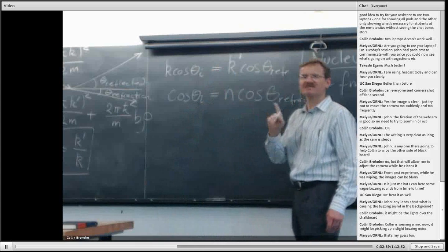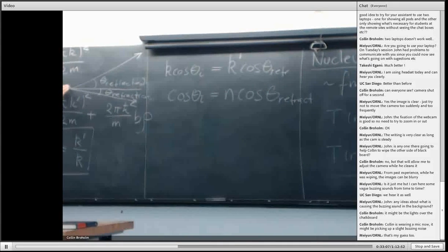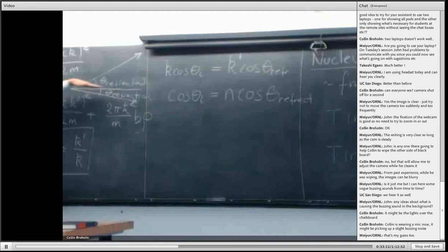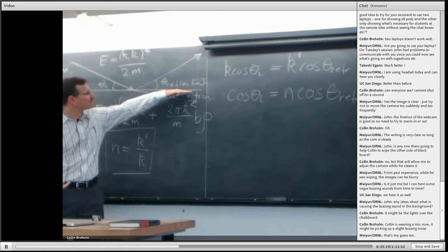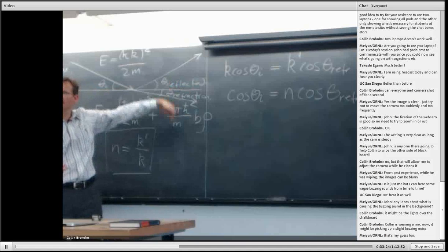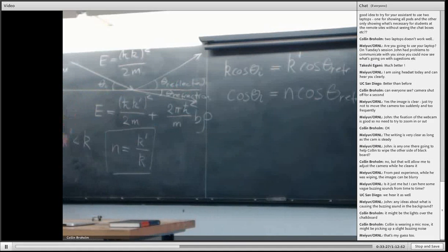Okay, and now here comes a very, very interesting property. Because if you can imagine reducing this angle of incidence, at some point I'm going to get to the situation where this refracted beam is traveling right along the surface. And at that point I have what's called the evanescent wave in the medium, and there's going to be an attenuation of the neutron density as I walk perpendicular to the interface in this direction. So all of that is exactly the same as in optics, because it's the same type of boundary conditions I'm dealing with, and the same type of plane wave situations.